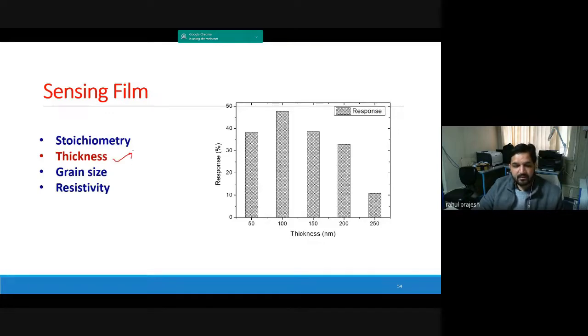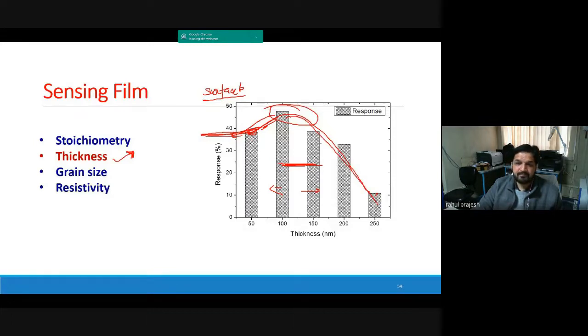You need to check what is the best thickness for your particular case. For example, I did some experiments and found that 100 to 150 nanometers is the suitable range for gas sensing application. If you see, this is a very low response, here also low response, but in between you are getting a very good response. So these are the ranges you should target. Why do you have low response in this region? It's a controversial thing, because in most cases, when you reduce the thickness, you get higher sensitivity because of high surface to volume ratio. But in this case, I see some decline, though most probably if I go even lower, I will see a saturated trend and it will not reduce further. But if you increase the thickness, it will keep on reducing. Why is that?